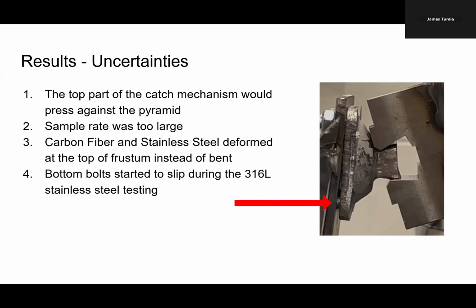For both carbon fiber and stainless steel, we noticed that instead of cleanly bending at the expected location, they started deforming near the top of the frustrum. That made it hard to generate the kind of bending moment we were aiming for and suggested some misalignment or setup issues. Finally, as seen in the picture provided, the bottom bolt slipped during the stainless steel test, which likely shifted the load path and reduced the accuracy of the test results.